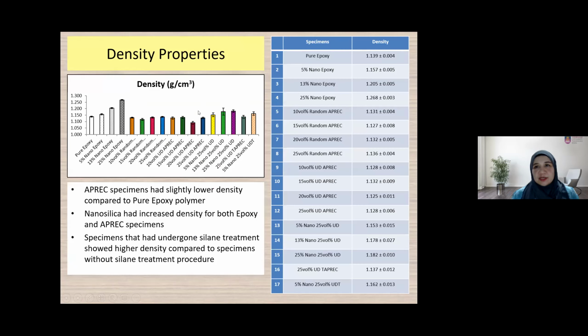Okay, so this is the density result. As we can see, the density of the pure polymer, the value at the right hand side, is about 1.14, in gram per centimeter cube. And if we put nanosilica from 5 to 25 weight%, the density slightly increased because the density of the nanosilica is higher than the polymer. So the density increases a little bit, from 1.1 up to 1.26 gram per centimeter cube.